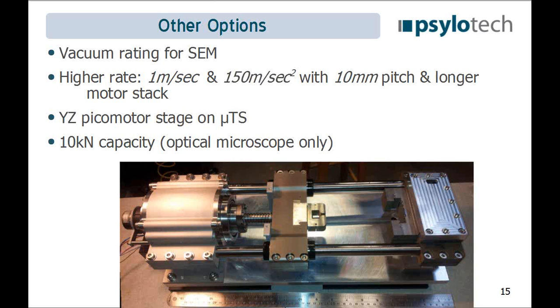Our goal as a company is to offer experimentalists a lot of flexibility to do different things. So the systems themselves have flexibility as well, in that you can configure them differently. For example, they can be vacuum rated so that they can go into a scanning electron microscope. We can make a faster system. Believe it or not, we can get to 1 meter per second with 150 meters per second squared acceleration, which is pretty fast out of this small load frame, if we extend the motor stack and put a 10 millimeter pitch instead of a 1 millimeter pitch. You lose a little bit of force capability, but if you need speed, we can tweak it for speed.